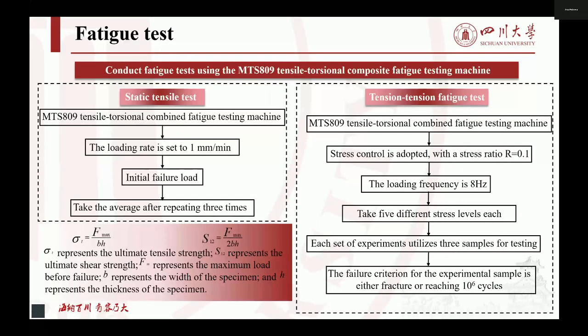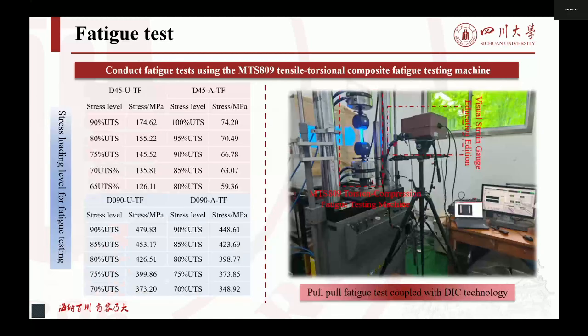Static tests were conducted using the MTS809 tensile-torsional composite testing machine, and the results of these tests served as the basis for fatigue tests. The fatigue tests were conducted at 5 different stress levels until the specimens fractured. It was considered that the specimens would not fracture when the number of cycles exceeded 1 million. This is the stress loading level for fatigue testing.